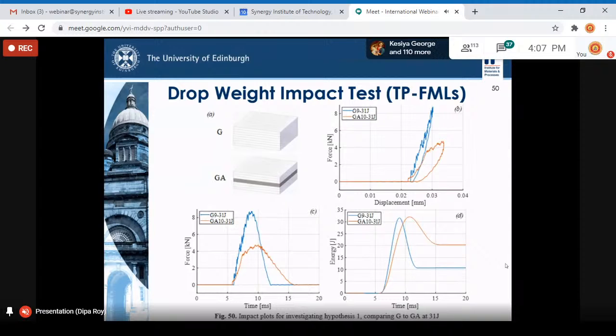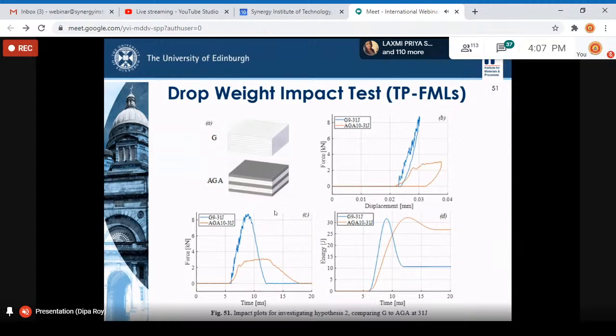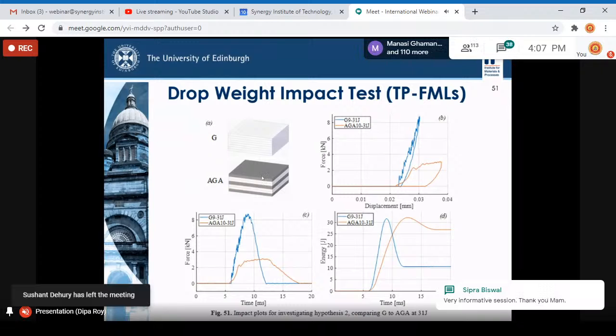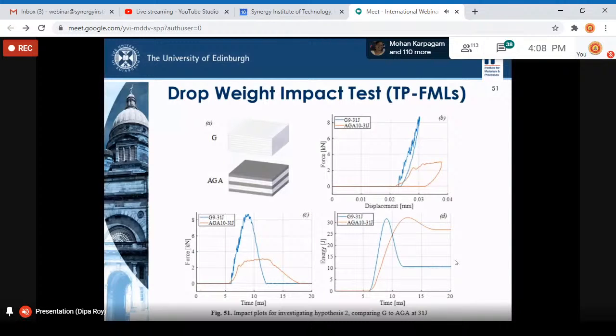Now, when we had 3 layers of aluminum, you can see we have 3 layers here. In comparison to a pure glass acrylic composite, the energy absorption behavior changes significantly again. Having 3 aluminum alloy layers, it absorbs much higher energy. It has aluminum alloy even on the surface, so when there is an impact, the surface can absorb a lot of energy. When this is dissipated throughout the bulk, there is again aluminum alloy, so the impact which reaches the lower level is much less. The overall absorption is much, much higher. This clearly shows the benefit of having these metal layers bonded with the glass fiber composite laminates.